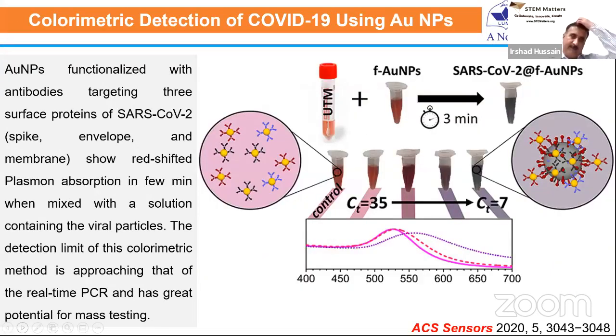And in yet another case, they functionalized gold nanoparticles with antibodies that are specific to proteins on viral particles, for example, antibodies which are specific to the spike, envelope, and membrane proteins of COVID-19. When they incubated viral particles with these gold nanoparticles, the nanoparticles attached to the viral particles, and due to their close distance, again they change their color from red to slightly blue, and you can clearly see this red shift in the plasmon absorption. These are very simple assays that can probably be used to develop colorimetric assays for the detection of COVID-19 using gold nanoparticles.